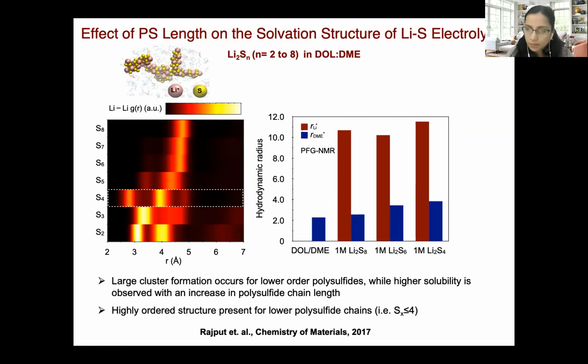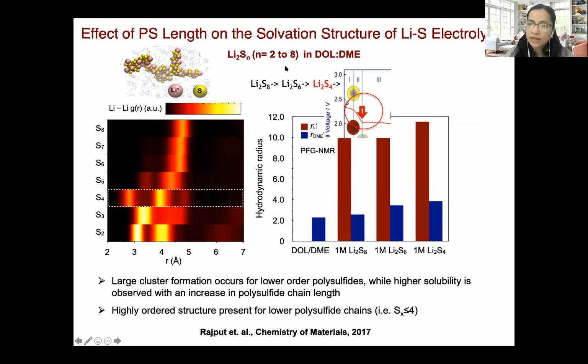So why is that a problem? Because if your Li2S4 is one of the dominant species present in the solution, such large cluster formation can suddenly increase the viscosity of the solution, which can result in this sharp voltage decline, which is observed in the second phase of the discharge curve.